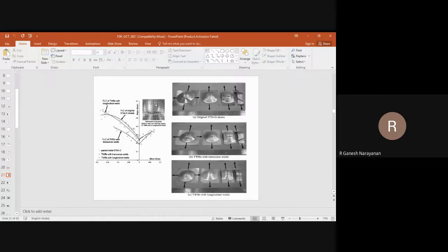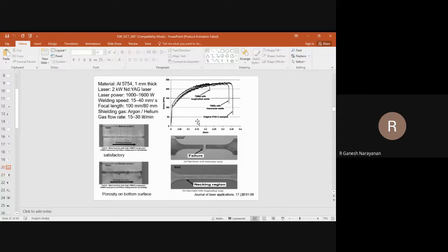And again, forming limit also is seen. You can see they have developed forming limit curves for longitudinal and transverse welds. And you can see that the original sheet, the raw sheet, has got better forming limit. So these are the deformed sheets for evaluating forming limit. See, I have not explained all that. There is a separate standard procedure to get the forming limit curve of any material, including tailor welded sheets, like you have a standard procedure to get stress-strain behavior.